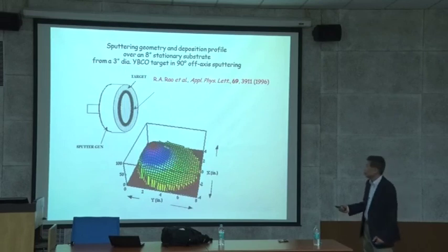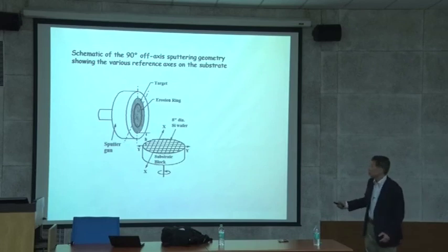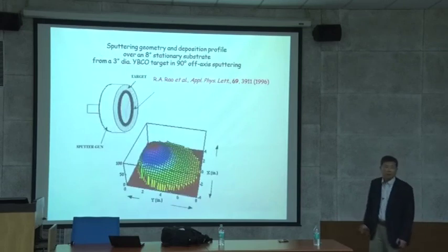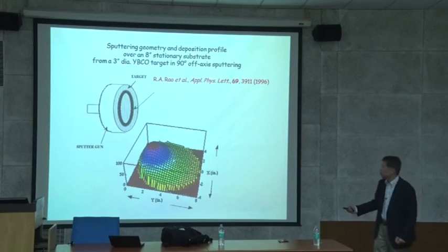In order to overcome this, it's done by just measurement of the matrix. You measure the thickness of this wafer, an 8-inch wafer area, for example. You have this whole 8-inch wafer, you deposit, measure the thickness, and get this profile. So this is a plateau or top region, but it drops a lot. Then you can find the rotation: you rotate this, average the thickness, and you can get a large uniform area. That can be done by finding exactly where the rotation axis is.